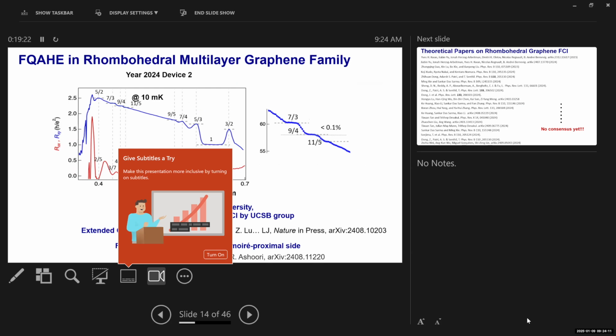And the quantization is pretty good, 0.1% within the value, and that's really limited by just the noise level of our experiment. This is not a single example - 5 is somewhat magic, but not that magic, because you can also get such fractional quantum anomalous Hall effect in 4-layer or 6-layer graphene, as long as you twist it close to 0 degree. And we have some other findings we call extended quantum anomalous Hall effect.